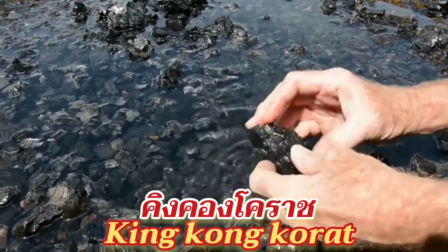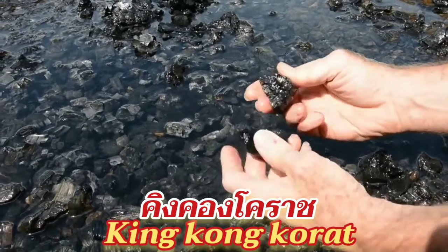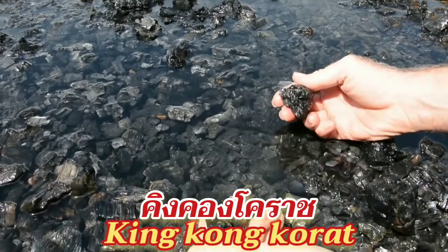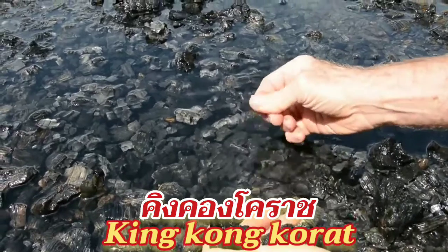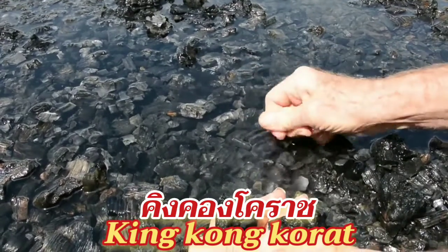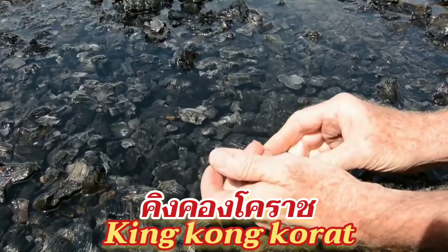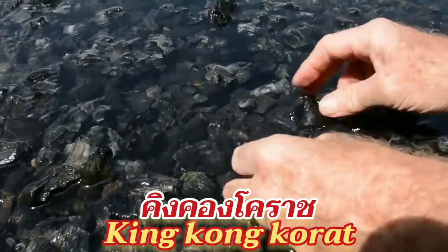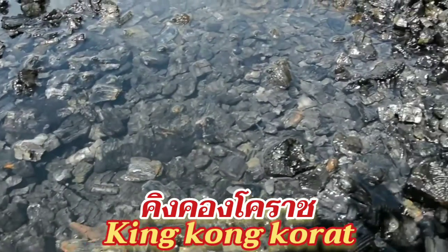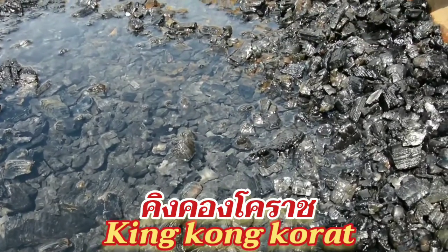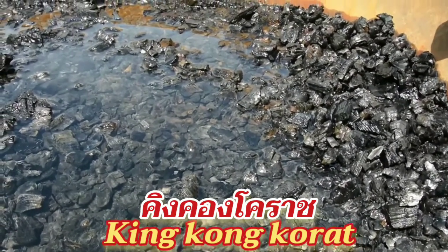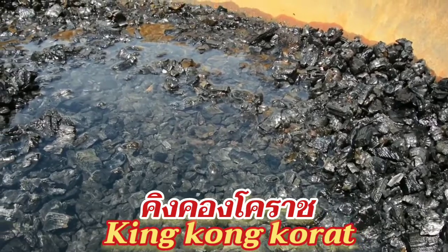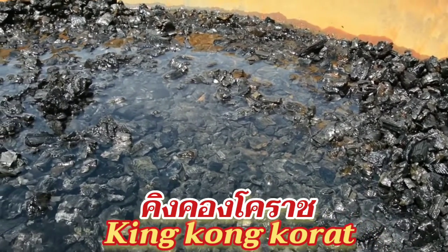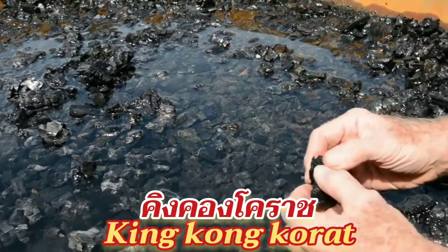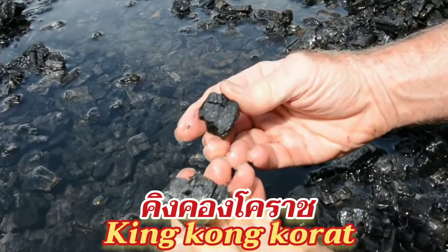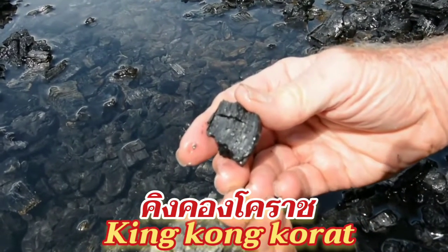Interestingly, the water is a little bit soapy on the feeling, so we'll measure the pH and look where that might come from. It seems that all of the pieces we can see here on the top layer are fully calcinated. There's no non-calcinated parts that we discovered. It breaks very nicely and you have beautiful biochar structure.